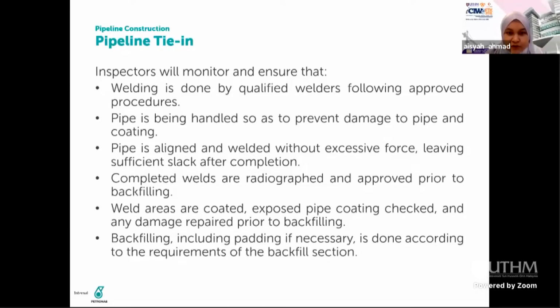This is where the field joint coating activities come in, and we need to ensure again that the exposed pipeline coating is okay, because external coating is the main protection against external corrosion. Usually for oil and gas pipelines we are using carbon steel, and it is quite susceptible to corrosion. So we need to ensure that the external coating is not damaged even before we are using it.